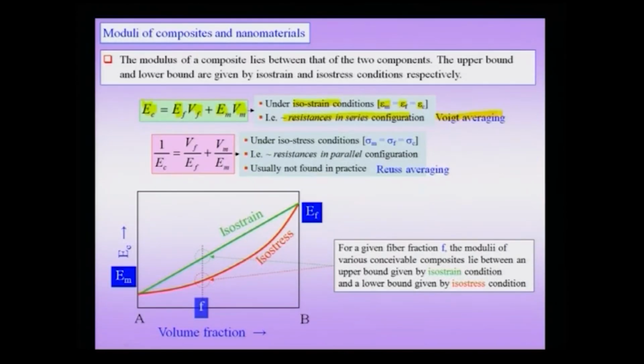The other extreme possibility is the isostress condition, which I pointed out, which means the stress in the matrix is the same as the stress in the fiber, which is the stress in the composite, and therefore this is like resistance in parallel configuration, and this leads to a formula like 1 by E c, E c being the modulus of the composite, equals V f by E f, the subscript f referring to the fiber, plus V m by E m, m being the subscript referring to the matrix. This kind of an averaging is called Reuss averaging. Therefore, I have two extremes of the modulus of the composite with respect to the volume fraction of the material.